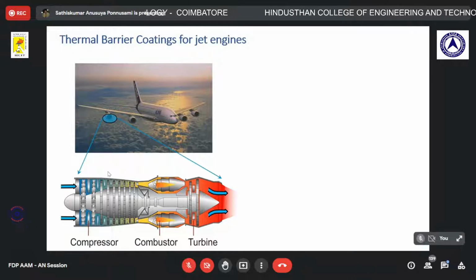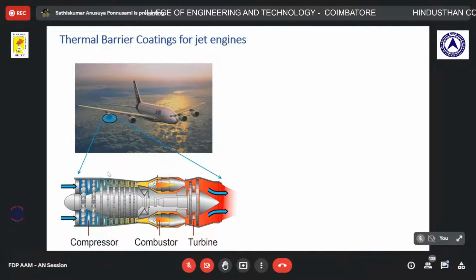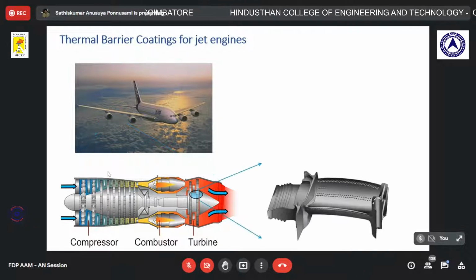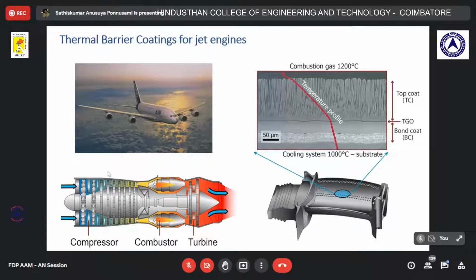sections. But of course, all of you would know these turbine blades are made of advanced metallic alloys, primarily nickel-based alloys, yeah, which can handle very good temperature, but not 2000 degrees. Yeah. So what we usually do is that we have these high-strength alloys, but on top of it, to withstand such very high temperatures, we basically coat these nickel blade alloys with ceramic coatings, and we call them thermal barrier coatings. Yeah, as you can see here, this is your blade, a typical nickel alloy blade, and on top of it we have a coating, and the microstructural picture of the coating is what you see here.